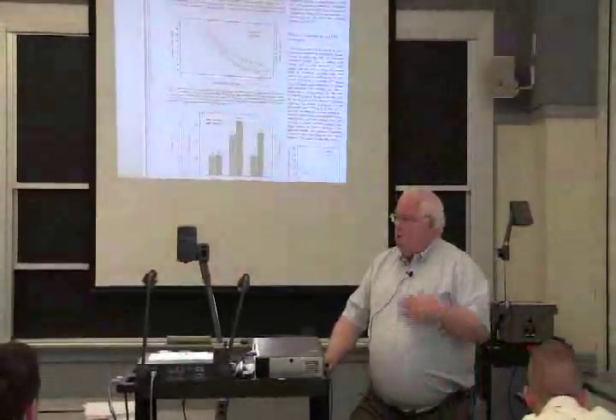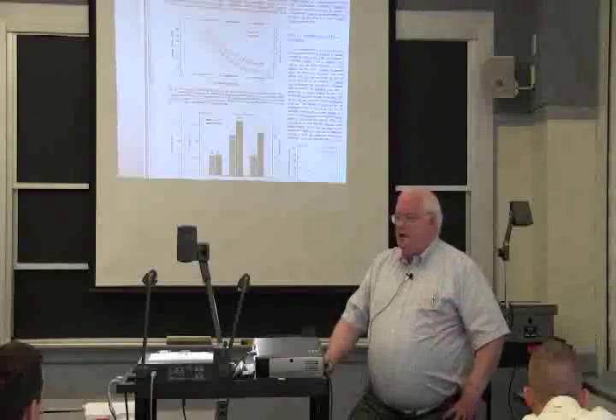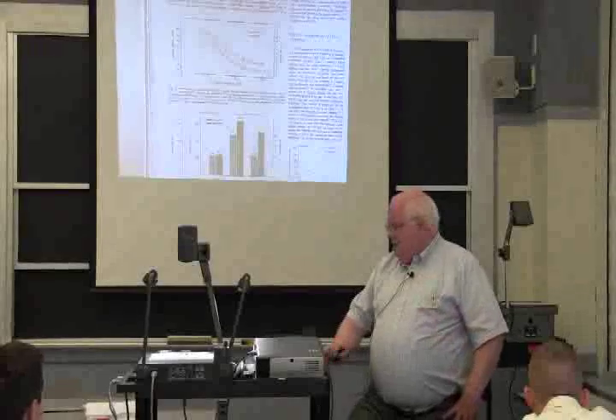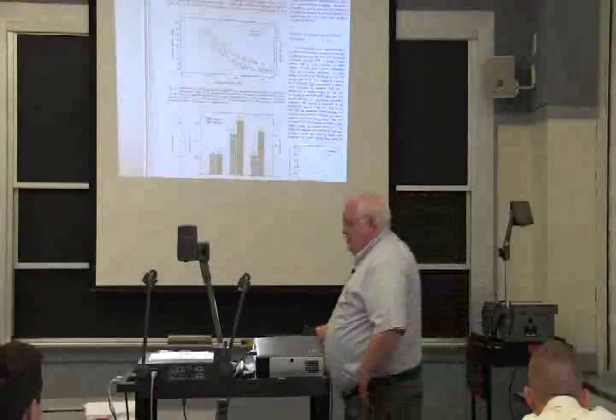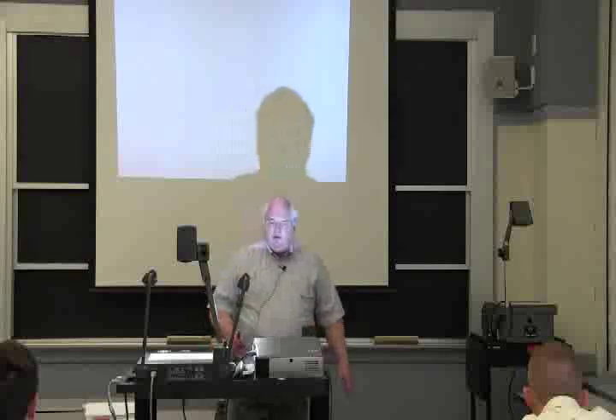So that's why you can afford to spend $1,000 an hour to put some of these things through there. And when you put them in the vessel, you're not just putting one disc or one cylinder in there, you're putting half a dozen discs at a time, so you spread it out a little bit that way. So hipping is one way to make a net shaped part.